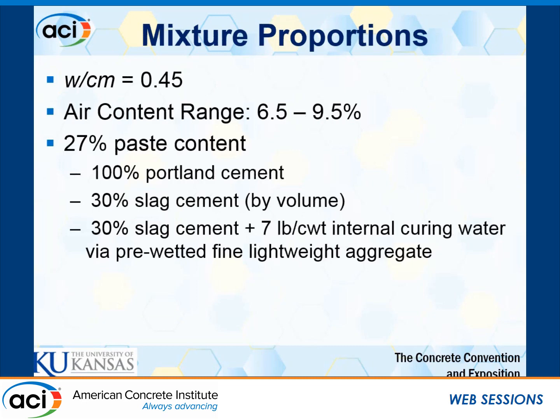Concrete properties that we used for this test program include a water-cement ratio of 0.45. We cast concrete when we get an air content between 6.5% and 9.5%. We used a total binder and water content of 27% paste volume. So for our 100% Portland cement mix, that equates to 593 pounds of cement and 267 pounds of water.